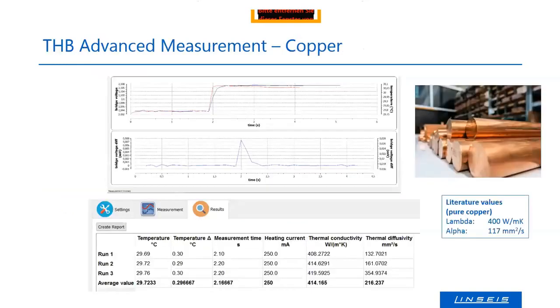And then we go to copper. You can see a plot from the measurement which we did. We did three measurements with pure copper, 99.999% copper. And we can measure the thermal conductivity, on average 414. The literature value is 400, so it's a good accuracy. It's a quite nice result. With the THB 100, it is not possible at all to measure copper.